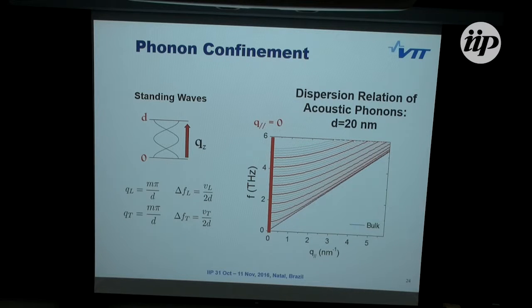And when one makes a thin membrane, then it means that there begin to appear standing waves, kind of phonon confinement, and then the frequency shift goes as 1 over the cavity thickness. So the thinner the cavity, the larger the shift, of course.